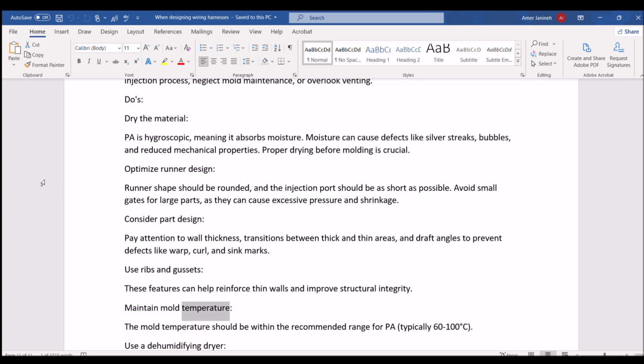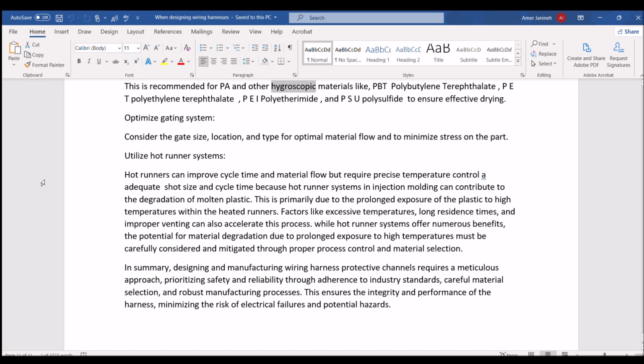Maintain mold temperature. The mold temperature should be within the recommended range for PA, typically 60 to 100 degrees Celsius. Use a dehumidifying dryer. This is recommended for PA and other hygroscopic materials like PBT (polybutylene terephthalate), PET (polyethylene terephthalate), PEI (polyetherimide), and PSU (polysulfone) to ensure effective drying. Optimize gating system. Consider the gate size, location, and type for optimal material flow and to minimize stress on the part. Utilize hot runner systems.